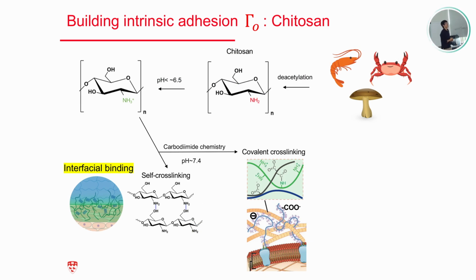And then, secondly, to enable this interfacial bonding, the polymer we utilize is called chitosan, which is a biopolymer polysaccharide derived from shrimp shell. These days you can get it from mushroom, and the characteristic of this polymer is that it carries a lot of primary amine groups, and at neutral pH these groups will be positively charged. And when positively charged, it enables attraction to the negatively charged surface of the tissue. And this primary amine, very basic chemistry, with carbodiimide, right? You can make a very strong amide bond, essentially the bond of protein, right? Between this adhesive and also the tissue. So for example, the extracellular matrix, like the protein of the tissue.